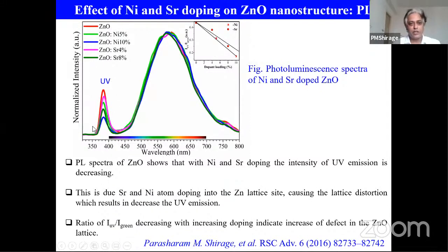If we normalize to the green region and take the ratio, the intensity at the UV region is changing. For example, pure zinc oxide has the highest intensity, and with replacement by strontium as well as nickel, the UV intensity is decreasing. And if we take the ratio of the UV to green intensity, it is decreasing with doping. That indicates that doping is changing the defect levels in this material. So we have seen that there is a change in the morphology, and because of the doping, there is a change in the defect levels in the materials.